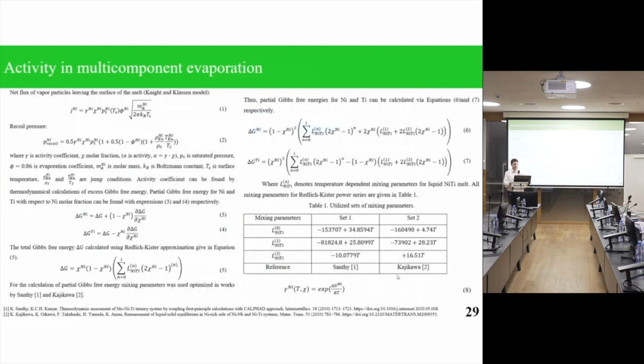And these calculations actually were performed to analyze difference in the evaporation kinetics for nickel and titanium components. So we need to calculate the flux of vapor particles, and for this we need to know the activity coefficient of nickel and titanium. And this was done based on the thermodynamic approach, so we can calculate the activity coefficient from the partial Gibbs free energy. The partial Gibbs free energy was calculated from the total Gibbs free energy, which in turn is presented by Redlich-Kister power series, which is known in literature for nitinol for various temperatures and compositions.